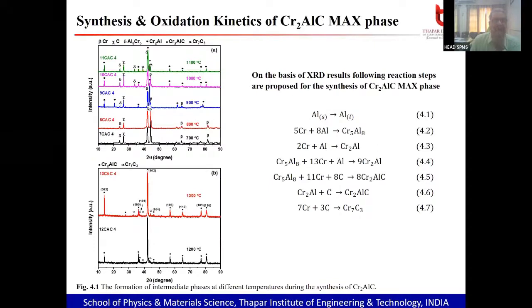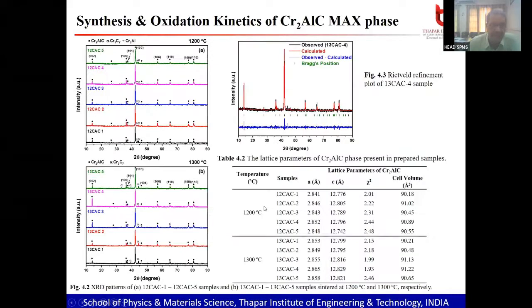What we have done is that after a lot of experimentation, we were able to succeed. And these are the possible conditions. After that, we have done the theoretical work also, the thermodynamic parameter measurements. Based on those parameters, we could predict the mechanism over here. So ultimately, you can see that at 1200 degrees centigrade and at 1300 degrees centigrade, we could synthesize the MAX phase here. So these are the possible parameters. We have done Rietveld analysis also in order to confirm whether we are right or not. A lot of calculations we have done. I'm not going to discuss all this part in detail, but simply briefly you can see.